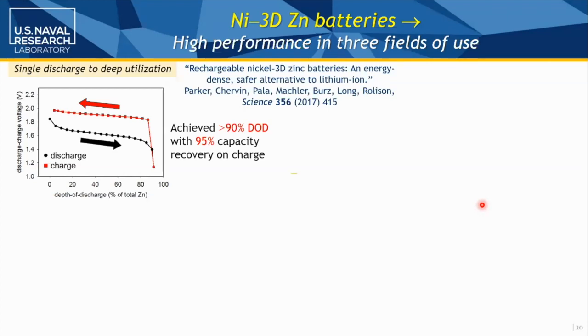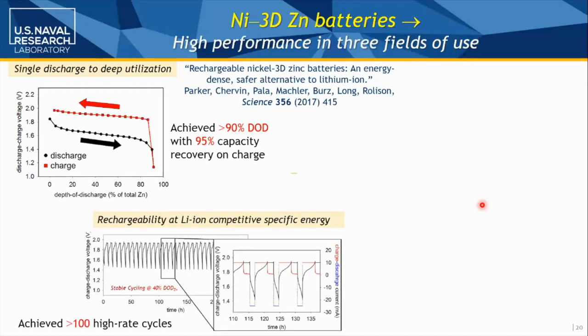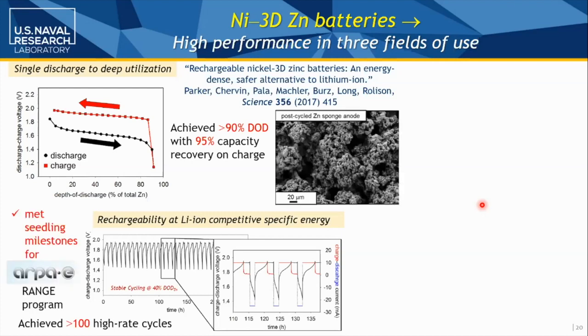Now, of course, in the battery, you're not trying to do that. So we had a one-year program from ARPA-E where we had to demonstrate that we could eat 40% of all the zinc in the sponge as we discharge and get all of it back and do that for 100 cycles at a high load, 25 milliamps per square centimeter. And nobody's solid state electrolyte's going to do that. And we showed that. We did it in a year. And we also showed sponge goes in, sponge comes out.